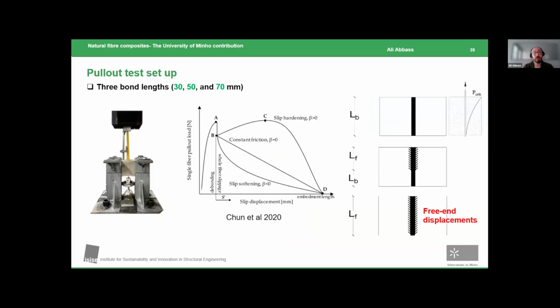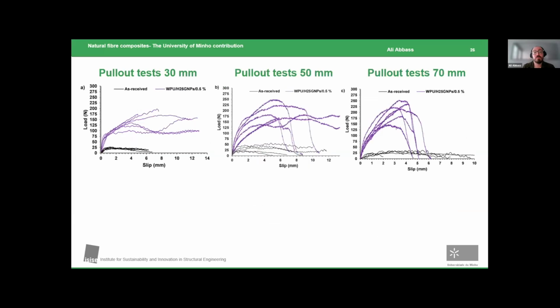A typical pull-out load-slip curve would show three distinctive phases. First, you have a linear elastic phase, where you have the adhesion intact. Then you have, at the loaded end, the starting of the debonding. And here you have a nonlinear phase where the bonded regions become unbonded, so you have friction and adhesion at the same time. And then you have the fully debonded region where the friction dictates the entire interface. Here you have the results before and after coating of the pull-out tests.